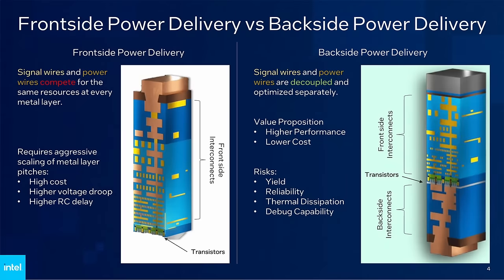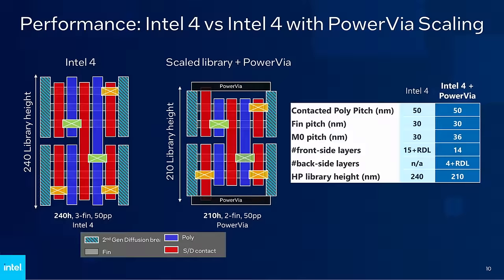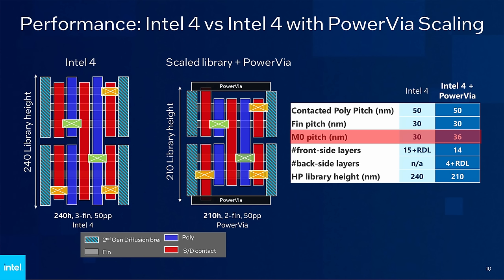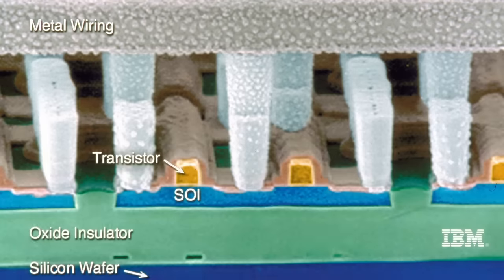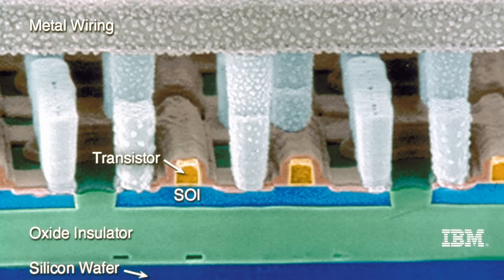Moving the power network to the backside of the chip leaves more room for the signal network on the frontside, which means you can implement a design that's strictly optimized for data signals. This allowed Intel to relax the pitch of the M0 metal layer. Instead of a 30nm pitch with the standard Intel 4 node, Blue Sky Creek with PowerVia uses a slightly larger 36nm pitch for the M0 metal. And even though it doesn't sound like much, this 20% increase in pitch size translates into a larger cost reduction, as the most complex part of the metal layers just became 20% less complex. And less complex means cheaper to manufacture.